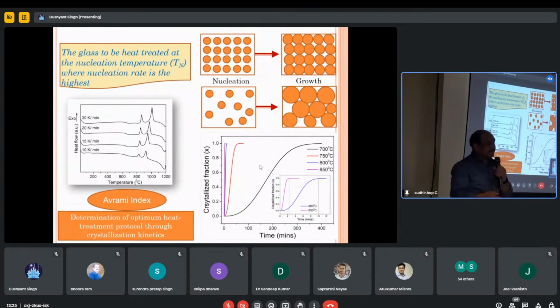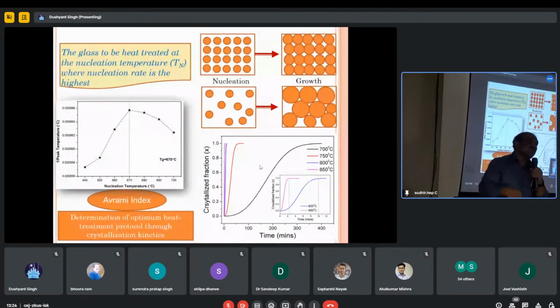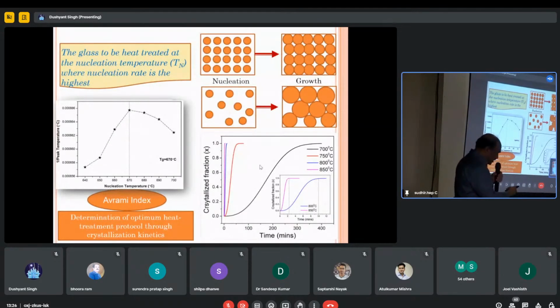So there is some technique so that you can ensure that a large number of nuclei is formed. We can do it basically through DSC studies. We can do some kind of analysis and we can determine experimentally the temperature for maximum nucleation. I am not going into the details of the theory, but you can determine the temperature for maximum nucleation and ensure a large number of nuclei in the glass matrix.